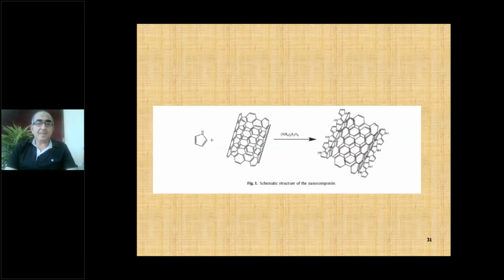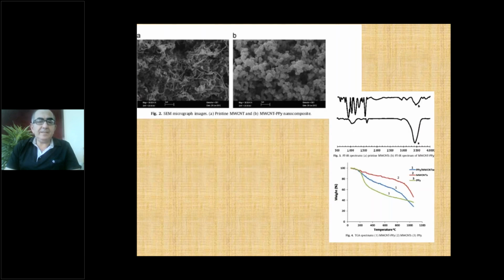This is a schematic structure of this nanocomposite. One of our colleagues is working on polymer chemistry. He synthesized these materials. These new materials we used after characterization. This is the image of these materials: first the pristine carbon nanotubes, then modified carbon nanotubes, and the infrared spectrum of these materials, also thermogravimetric analysis results you can see.